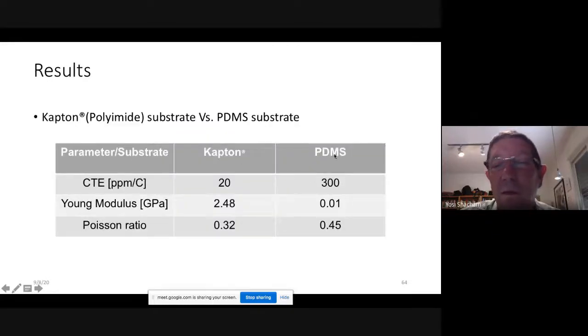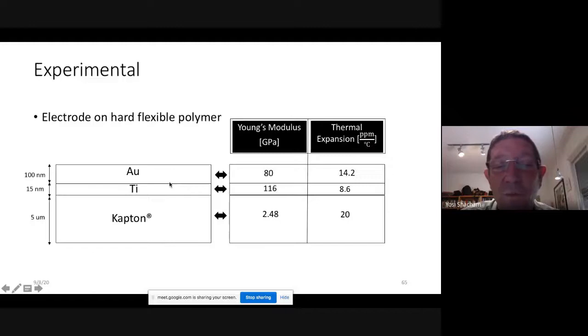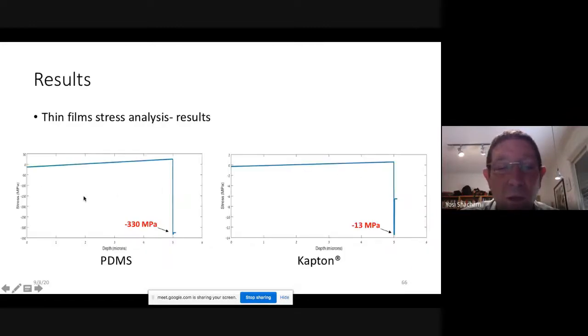And this is the CTE of gold. This is Young's modulus of gold, this is the Poisson ratio. So this is the problem. PDMS has a huge coefficient of thermal expansion. So we need to reduce the coefficient of thermal expansion of the polymer. So one option is to switch to Kapton. It's less flexible, but with much, much less coefficient of thermal expansion. And we did, again, the calculation and found out that for Kapton, the stress is only 13 megapascal, and the